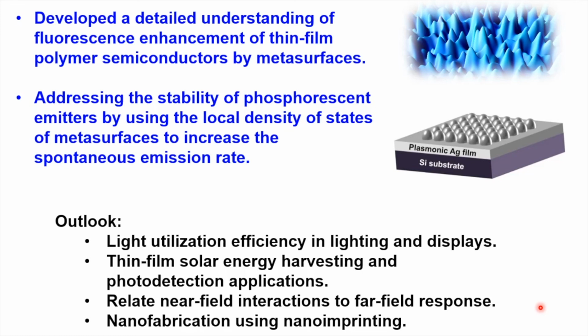In general, especially when you're talking about coupling emitting materials to metasurfaces, there's a need to relate the near-field interactions to the far-field response. It's not always easy to predict what the cause of the emission enhancement is, and that really needs to be studied both in the near-field and the far-field. Finally, to have commercial viability for these metasurfaces, they need to be fabricated at a large scale and low cost, probably using nanoimprint lithography and roll-to-roll processing. These technologies haven't been developed enough to make this happen, so there's clearly a need for a lot of research in that area.